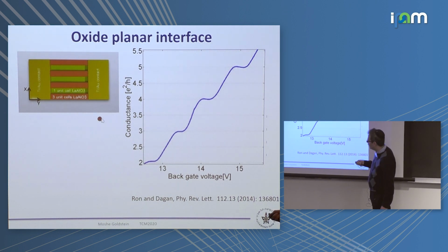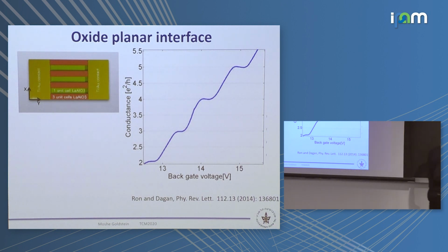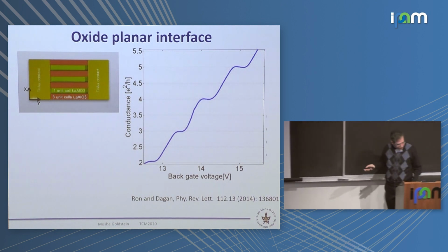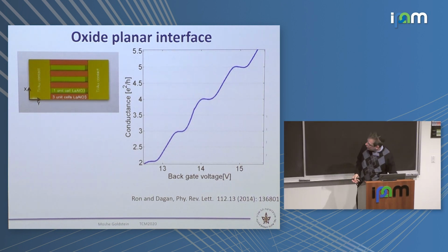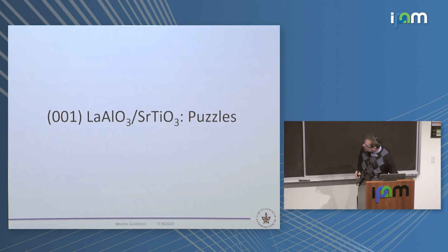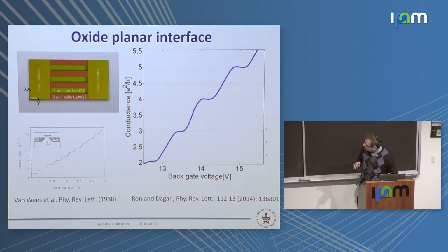And this is pretty surprising that you see those nice conduction steps, because this is a few microns long, and the material is not extremely clean or high mobility, so you would expect backscattering. And another surprising thing is that the steps are in units of 1 e²/h, not 2. So maybe spin is somehow broken. So this is still not yet understood, but maybe people in the crowd will get interested. In any case, those are published results by my colleagues. And okay, so this is not what I'm going to discuss.